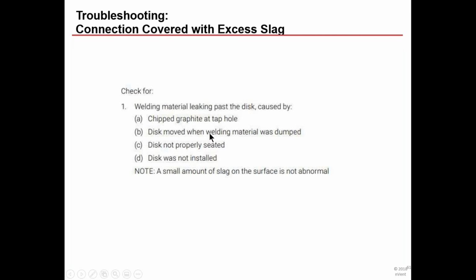Connection covered with excess slag. Again, that chipped tap hole. The disc moved when the welding material was dumped. Disc not properly seated, or disc was not installed. Again, with the Cadweld Plus, you don't have to worry about placement of that disc. It's built to provide the necessary time for that to happen, where the slag and the copper separate.